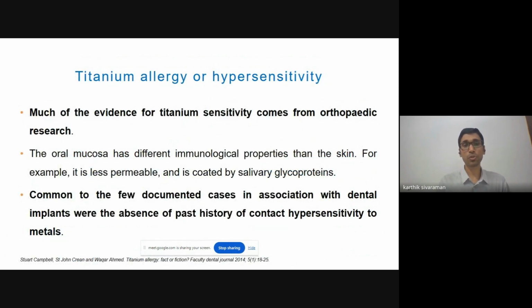So much of this evidence for the so-called titanium sensitivity is coming from orthopedic research and not dental literature. We also need to understand that the oral mucosa has a different set of immunological properties compared to skin. For example, it is less permeable and is coated by salivary glycoproteins. For instance, the studies say that at least 5 to 12 times the concentration of allergen has to be present for eliciting an allergic response for titanium. However, we need to note that there are a few documented cases in association with dental implants. But common to these cases is the absence of a past history of contact hypersensitivity to metals.